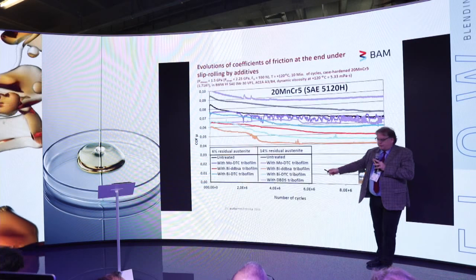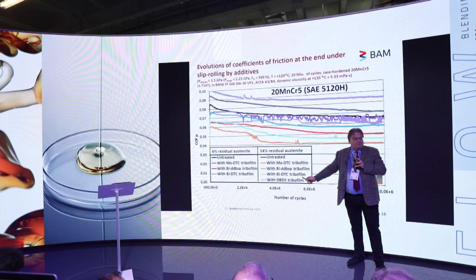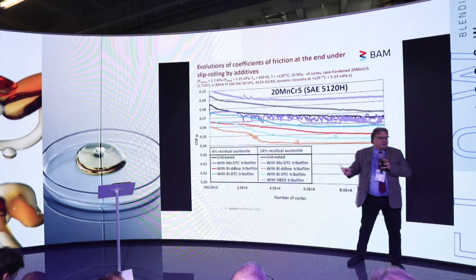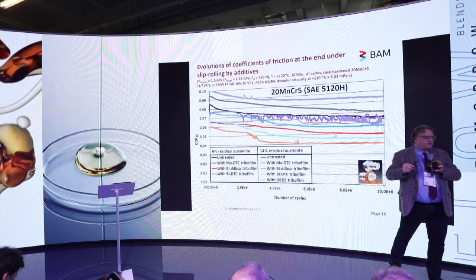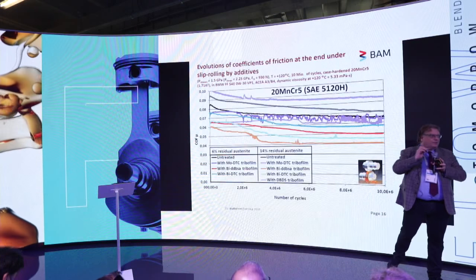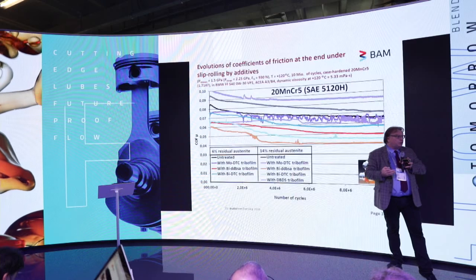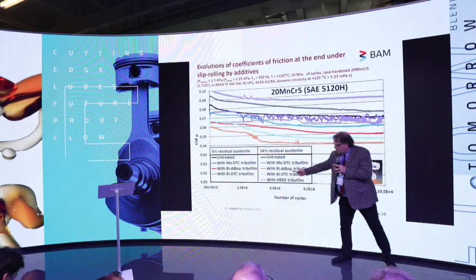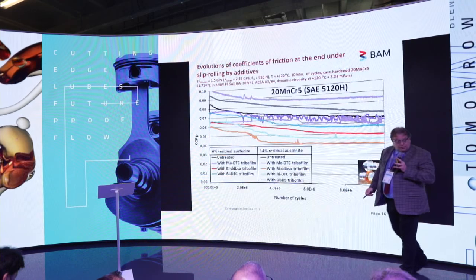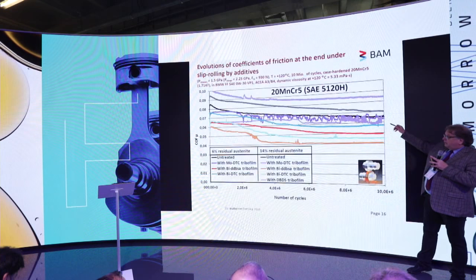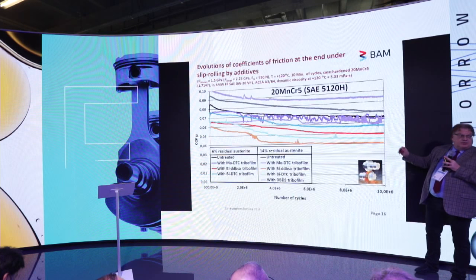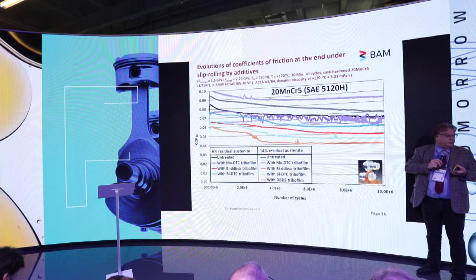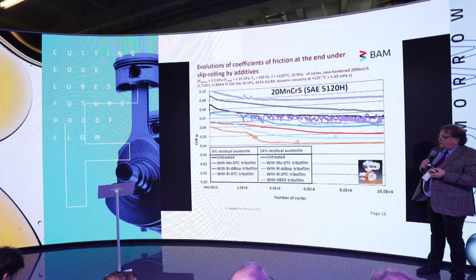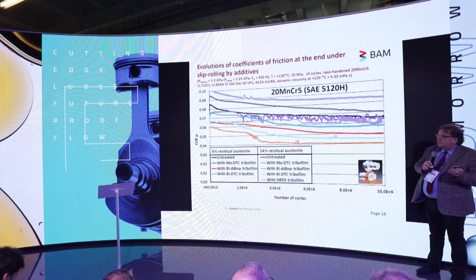And now you use non-toxic bismuth. Ladies may know the bismuth because it's the gloss in the lipstick. Yeah, so it's a heavy metal, but it's non-toxic. You take different bismuth compounds, and then you can reduce friction significantly in a gear oil.